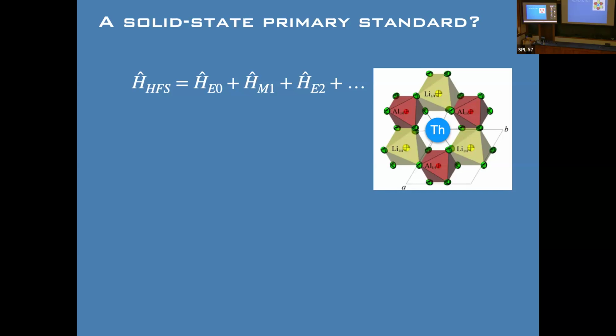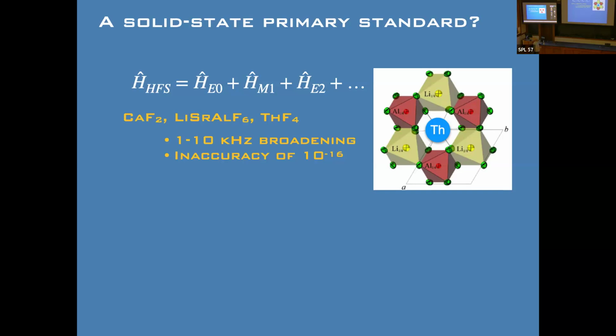So I walked you through this and said, we have this thorium doped into this crystal, and there's this sort of multipole Hamiltonian. We can think about all the perturbations of the crystal on the nucleus, right? And the takeaway is that at the end of the day, there are few kilohertz broadenings that come about from the fluorine nuclear spins interacting with the nucleus. And then there's an inaccuracy of the clock at about a part in 10 to the 16. This is about the definition of the second. And that's because of temperature dependent shifts. And so the question is, can we get rid of those?